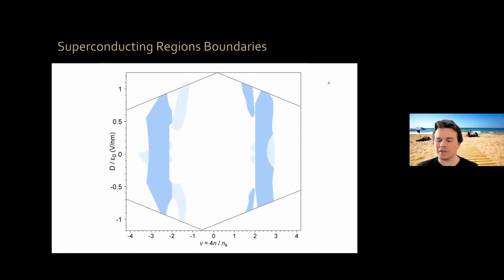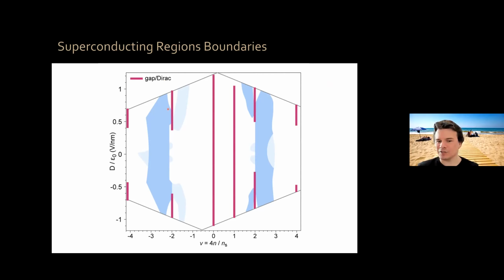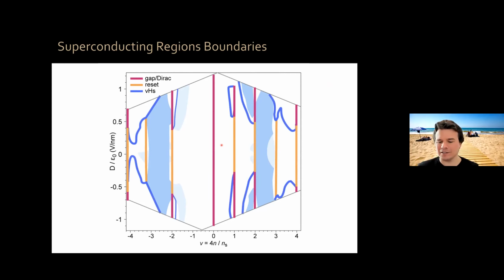And now I'm going to put on top here schematic lines showing the places where we have these three different behaviors in the normalized Hall density. Regions where we have this gap Dirac type of transition behavior are shown here in red. Regions where we have reset type of behavior are shown here in yellow, orange. Regions where we have van Hove singularity type of transition behavior are shown in dark blue lines. As you can see, a very interesting thing emerges. At 0 displacement field or at small displacement field, superconductivity is mostly bounded by resets between filling factors 2 and 3, -2 and -3. But then at high displacement fields, the superconductivity is bounded by van Hove singularities or gap Dirac regions, for the most part.